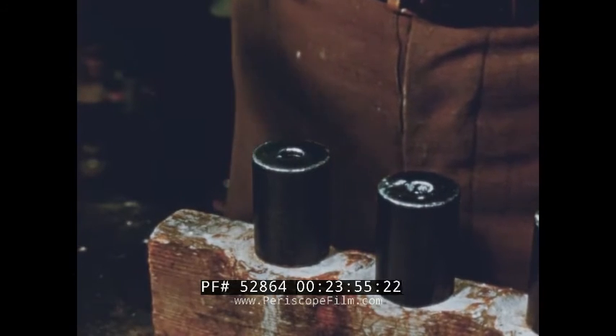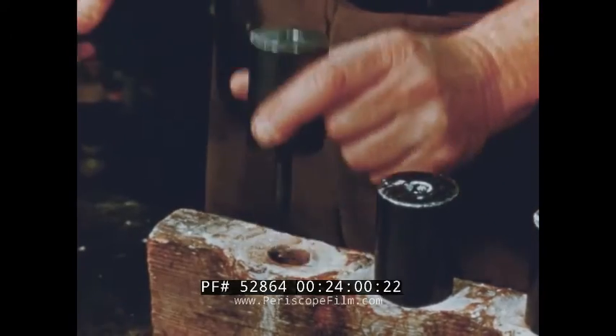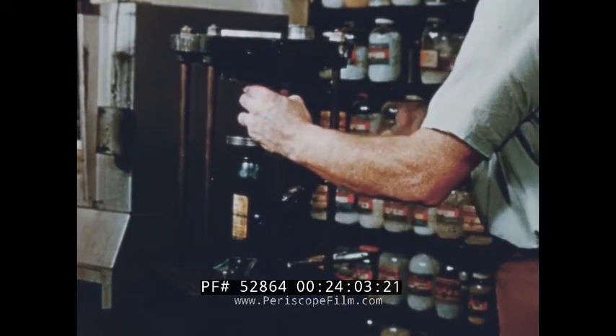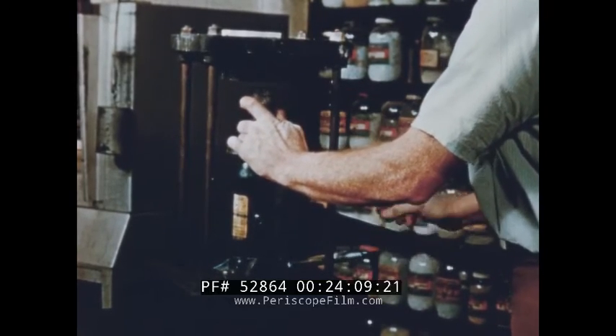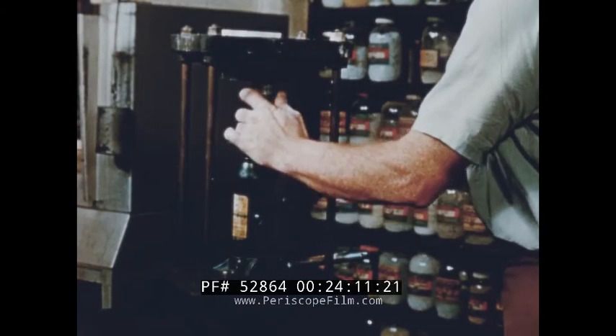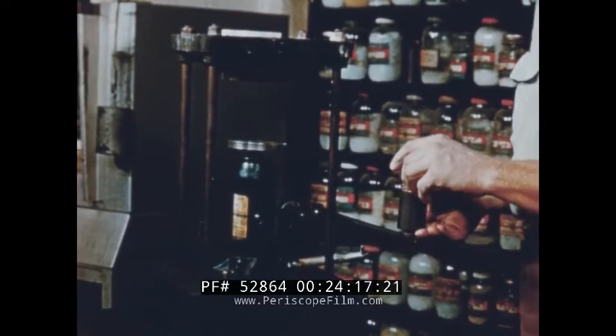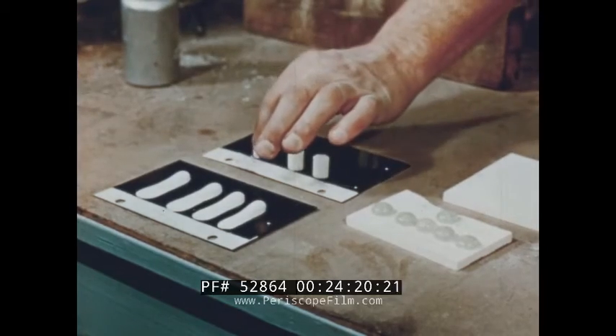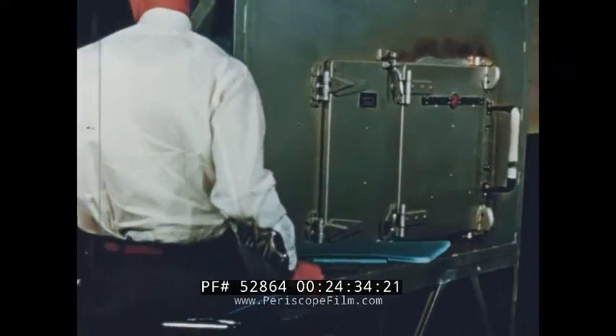Water is added to the frit sample, which is put into a cylinder. Then a hydraulic pump compresses the frit and water into a small cylindrical form, placed on a steel plate for firing along with approved standard samples from the same type of frit. When placed in a furnace and heated, the melted frit shows its rate of flow and fusion compared with that of the standard. Glazed frit from the milling department is tested with standard samples for color, opacity, and softness — called the button test. This special furnace is designed for testing in the development and control of aluminum enamel frits and colors.